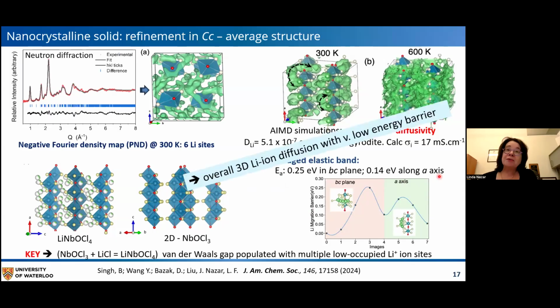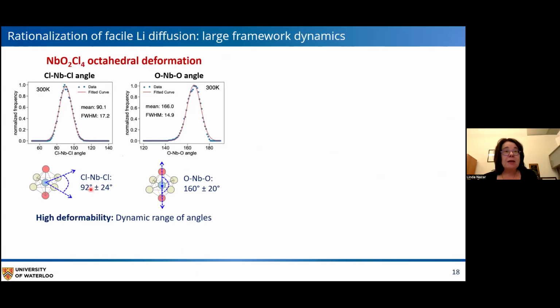So overall, we have three-dimensional lithium diffusion and a very low energy barrier. We have these fairly weakly bonded sheets of niobium oxychloride with lithium free to wander in both the bc plane and along the a axis. Now, this freedom translates into some very interesting anion dynamics. So this shows the octahedral deformation of the NbO2Cl4 units, which are effectively these units.